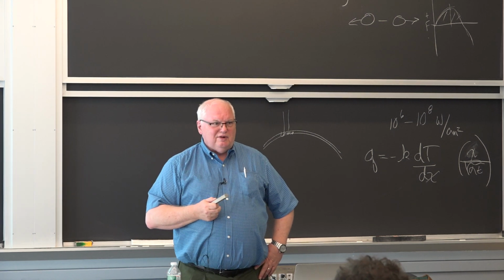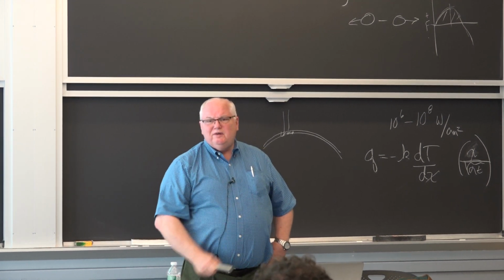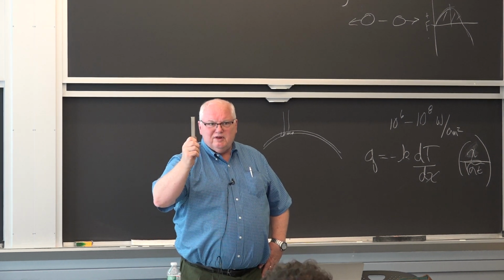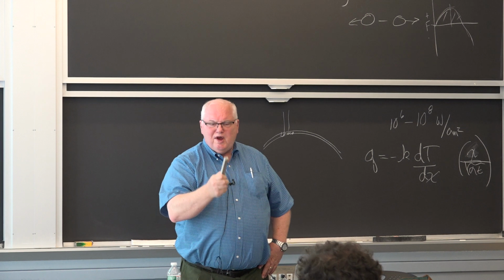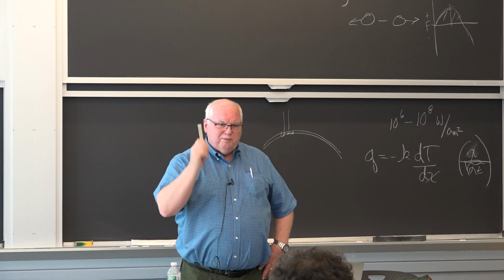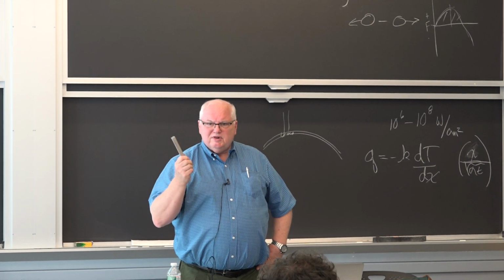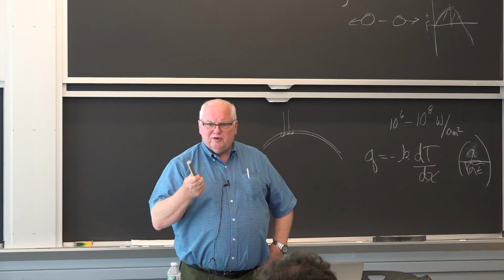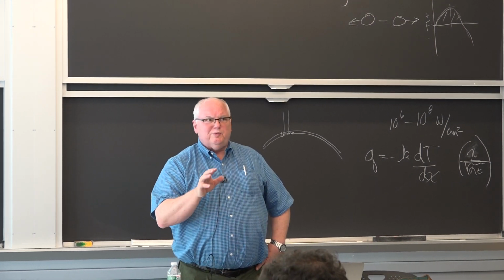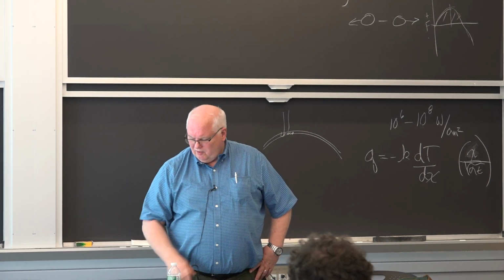I gave you that lecture the other day, right? This has to go to the people, and you're going to have to meet those specs. You have to make at least 100 of these before you can even get enough statistics. It says you have to do 10 heats, or 10 lots you might call it, and 10 samples in each lot to get the statistical process control data. So the FAA believes that you can reproducibly produce a product to go into the aircraft.